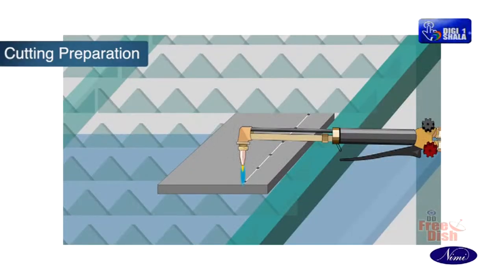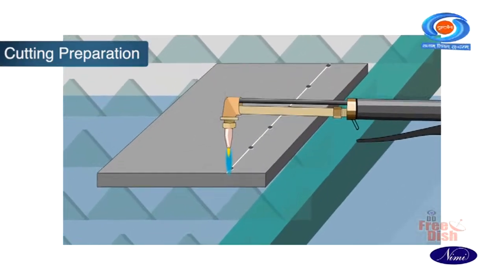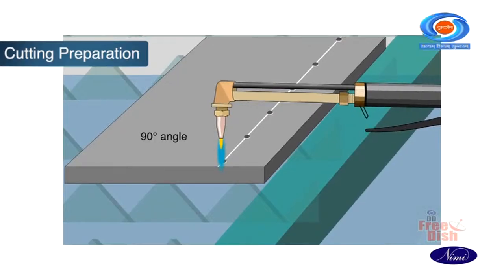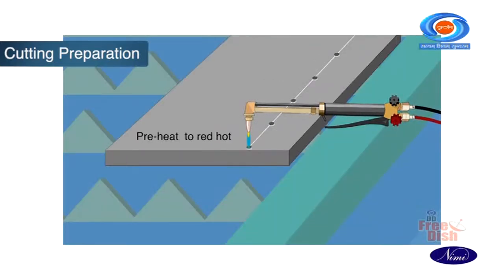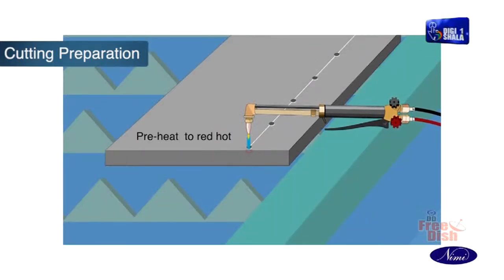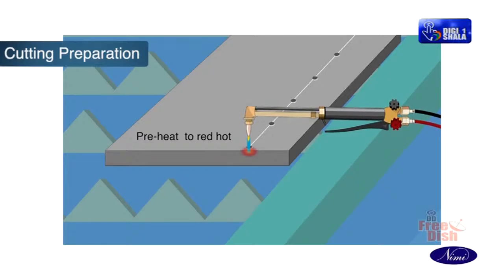Set the neutral flame. Hold the blowpipe at an angle of 90 degrees between the line of cut and the cutting nozzle axis, and between the nozzle and the surface of the plate. Preheat the starting point of the punched line to red hot condition.